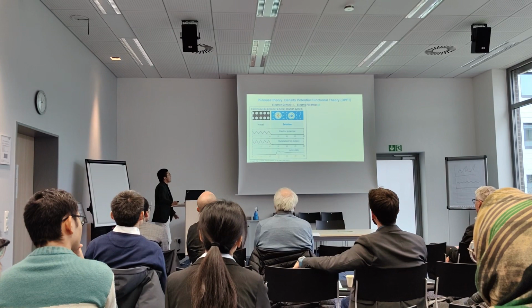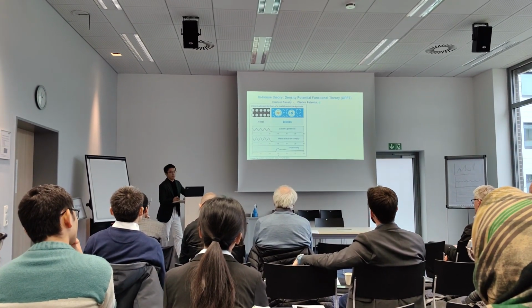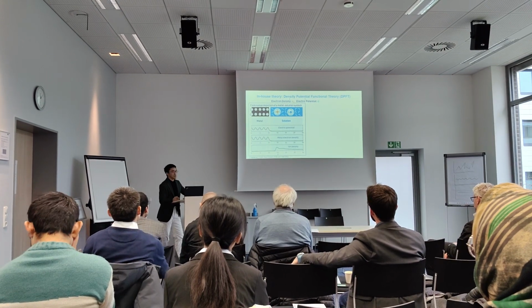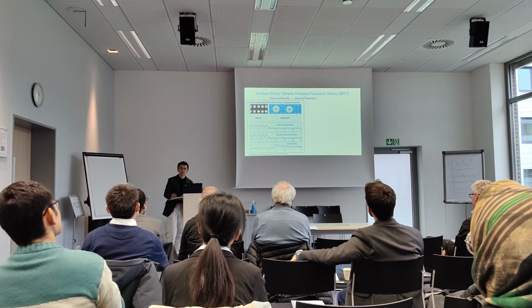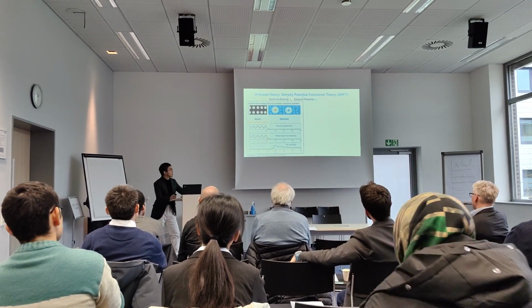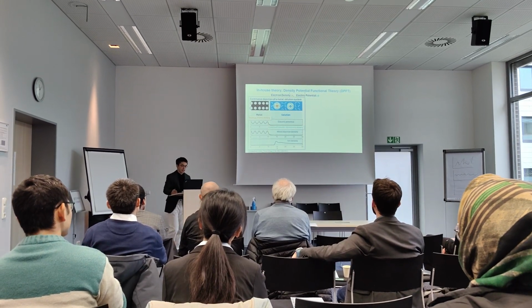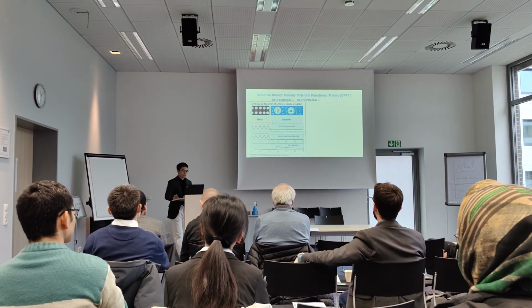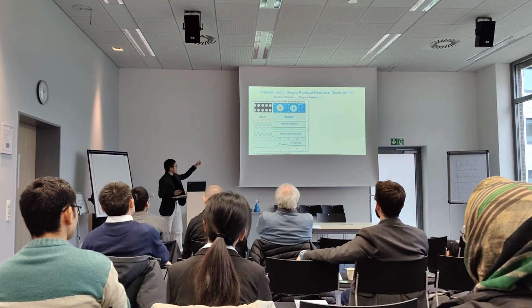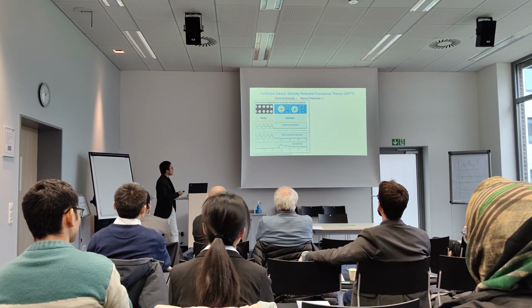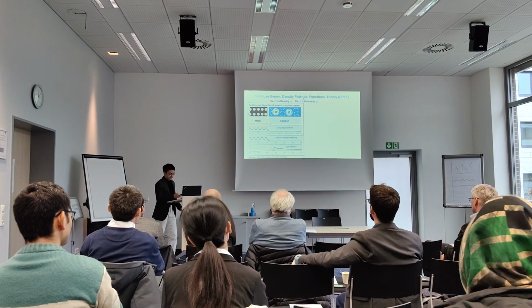In this theory, the electron density and electric potential are the two core variables to solve for. This allows a continuous depiction of the metal-solution system from the metal bulk to the solution bulk. The quantum mechanical nature of the electron is captured by Thomas-Fermi theory, while the classical charged fluids are captured by a modified Poisson-Boltzmann theory. And you can see the electric potential, the metal electron density, ion density, and solvent density can all be captured.